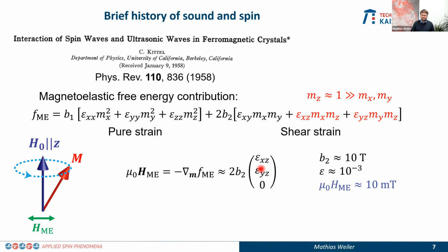And in his work, Kittel made the assumption that one can neglect the mx and my components, as they are much smaller than the mz component. And then one sees that the dominant components that remain are those that contain an mz, and those are these shear strain components. So that is kind of the original idea. There should be an interaction. Whenever there is a strain, it generates a virtual magnetoelastic field, and one can easily estimate the magnitude of that field that can be achieved.